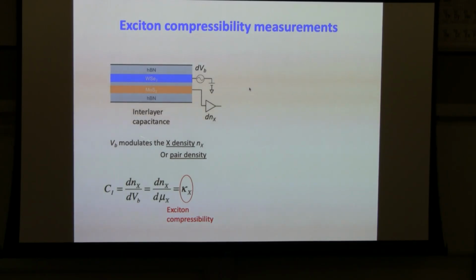All right. So note that the VB actually modulates the pair density, so that the interlayer capacitance is equal to dNx, the pair density change, divided by the voltage bias modulation. And remember that VB is actually equal to the exciton chemical potential. As a result, this interlayer capacitance will provide a direct measurement of the exciton compressibility of the double layer.